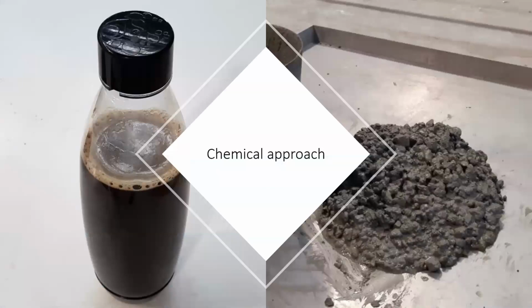So everything that said before had led us to the chemical approach. In 2019, after observing the low absorption rate by the physical approach, that was a 10% CO2 absorption, we came up with a new chemical approach. The claim here is more than 90% absorption rate. And as you can see, we had also solved the workability issue on the right-hand side picture in a way that recycled concrete is now flowable in a degree comparable with self-compacting concrete.